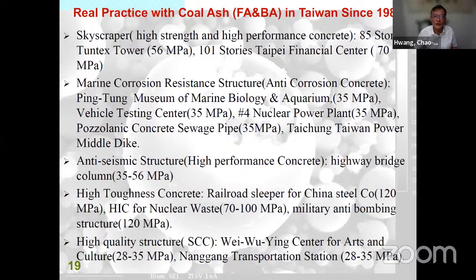We use fly ash, bottom ash to make a road, paver road. So that it's a pavement from the sea structure, water structure, and anti-seismic structure, high-performance concrete. So a highway bridge from 35 to 56 MPa, high performance concrete. So in Taiwan steel, China Steel, all the railway sleepers I designed for them are 120 MPa. That is a very high strength, 17,000 PSI.